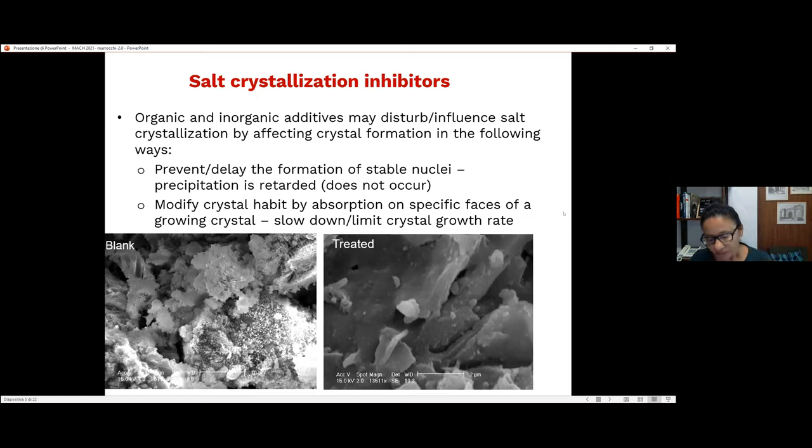One way to prevent the crystallization inside the pore, and therefore the stone breakage, is to treat the porous material with a substance that inhibits subflorescence in favor of efflorescence. These crystallization inhibitors indeed reduce the pressure associated with the growing crystal, trying to keep it below the breakage point.